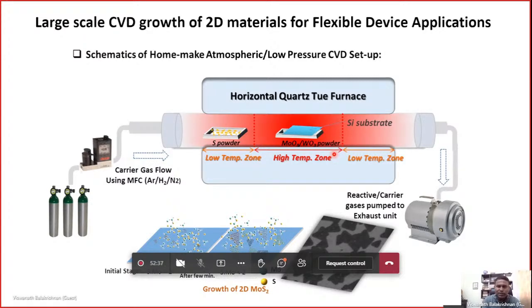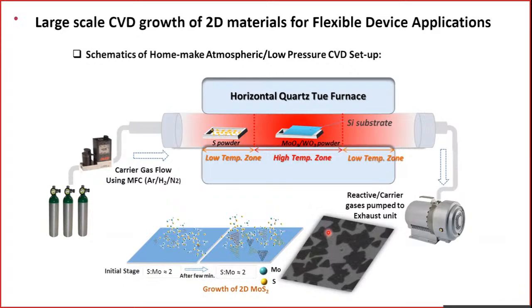Of course, in terms of 2D materials growth, we need to also make sure that the flow is important. The flow rate, right? We don't want to have a turbulent flow. A laminar flow is important. Of course, we need to look at the Reynolds number and so on. Based on the tube diameter, the right flow rate has to be adjusted. And the second aspect is that the concentration of the precursor is also important. With very high concentration, typically a vertical, three-dimensional growth will take place. You would not get the actual 2D growth. Typically 2D growth, right, where the advancement of the edges, your growth interface has to move laterally on the surface. That typically happens at relatively low concentration.